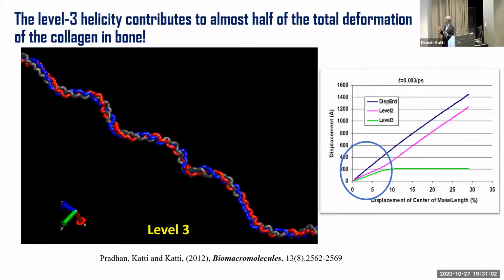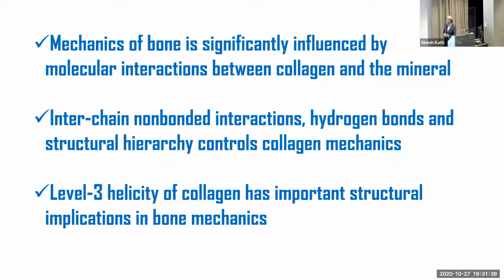And so we did a lot of simulations, and what we found was that level 3 helicity contributes to almost half of the total deformation or stretch of the collagen and bone. So that is significant. And up to this point, it was not even known that there was a level 3 helicity there. But the level 3 helicity during the normal day-to-day activities of a human being contributes to half of the stretching or deformation. So the takeaway or the summary of this work on bone is that mechanics of bone is significantly influenced by molecular interactions between collagen and the mineral. Interchain, non-bonded interactions, hydrogen bonds, and structural hierarchy control collagen mechanics. And level 3 helicity of collagen has important structural implications in bone mechanics.